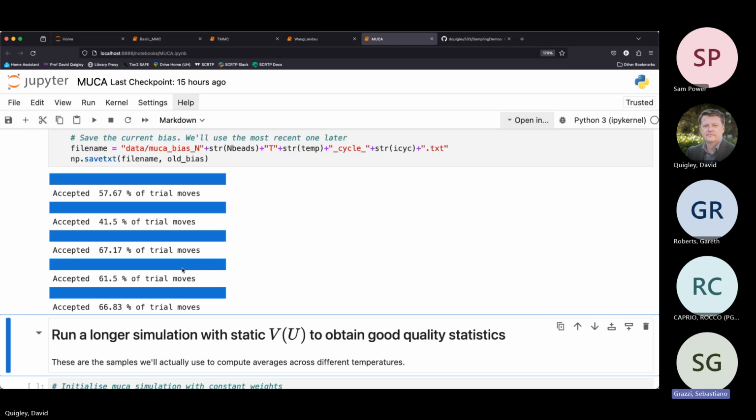So I've got two modes. I know the modes very well because they're 2 crystal structures. So I know this one's FCC, this one's BCC, or this one's diamond, this one's hexagonal diamond. I know exactly where the minimum of that mode is, or the maximum if I'm talking about probability. So I define my microstate coordinates relative to that minimum. And then I've got a Monte Carlo move that just shifts the origin, shifts which minimum I'm taking as the origin. So it takes me in one move from one crystal structure to the other.